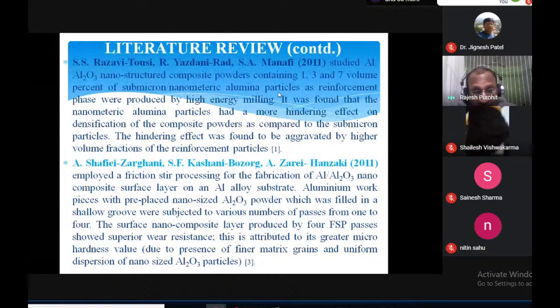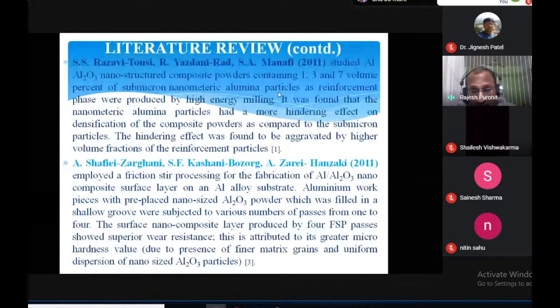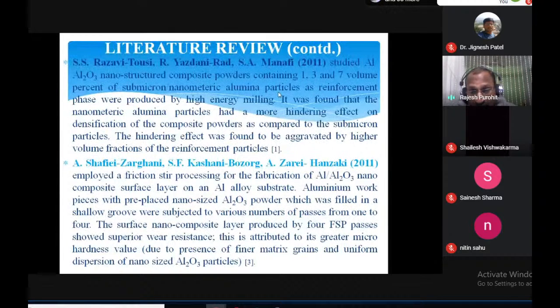This shallow groove was subjected to a rotating tool run on the groove, with the number of passes of the rotating tool varied from 1 to 4. The surface nano-composite layer produced by 4 FSP passes showed superior wear resistance. This is attributed to its greater microhardness value, because the nanoparticles are mixed on the surface of the aluminum substrate, and because of that hardness is increasing, and wear resistance also increases. This is due to the presence of fine matrix grain and uniform dispersion of the nano-sized alumina particles.